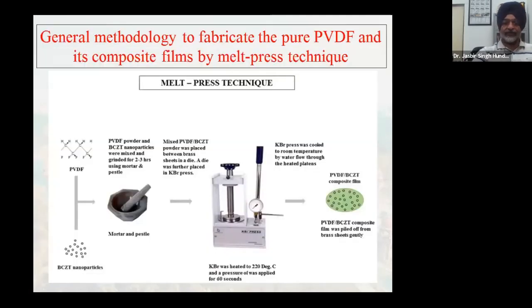So this is the melt press method we have. We have PVDF, and we are using PVDF as a matrix basically, and we use BCZT nanoparticles which are spread in the PVDF matrix. After grinding them, they are put here in this melt press, where we have metal foils on two sides, and we press the film. We heat the film and then we press. The basic unit is a hot press machine. A similar thing we also tried earlier, but this time we are trying it on this composite of polymer and BCZT nanoparticles.